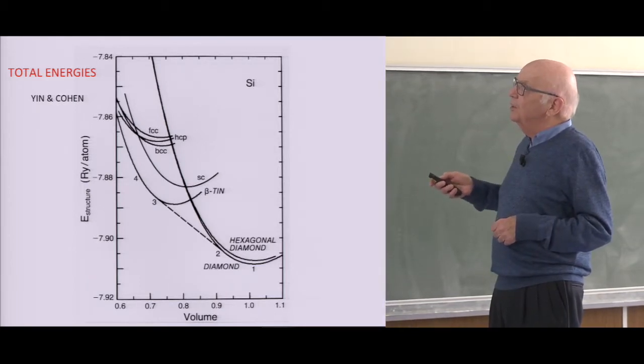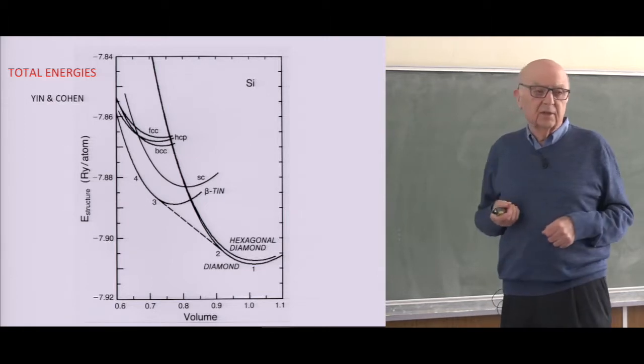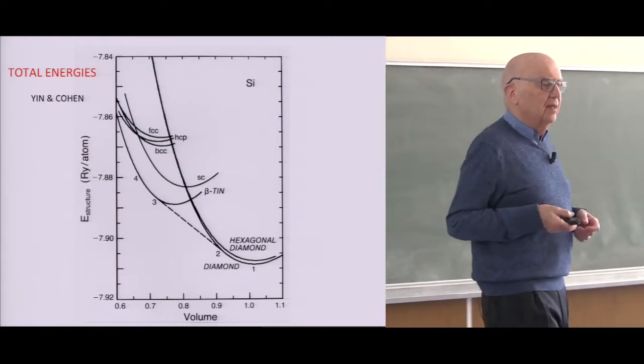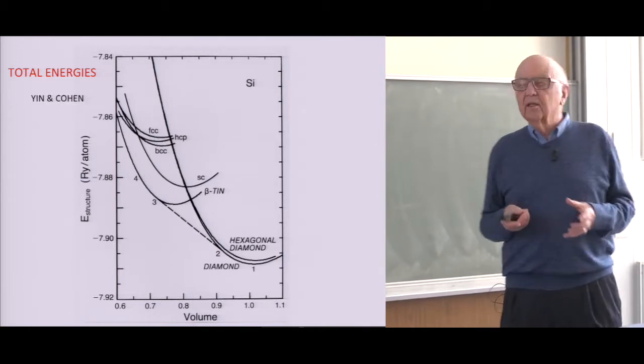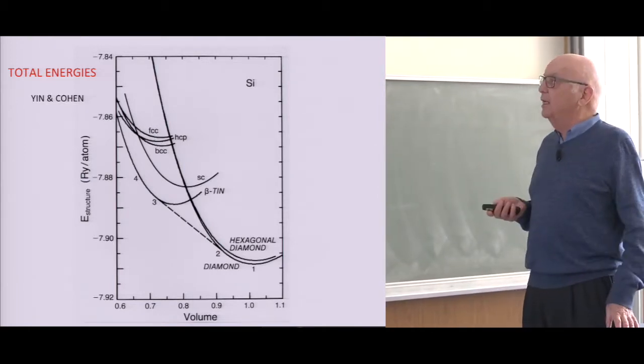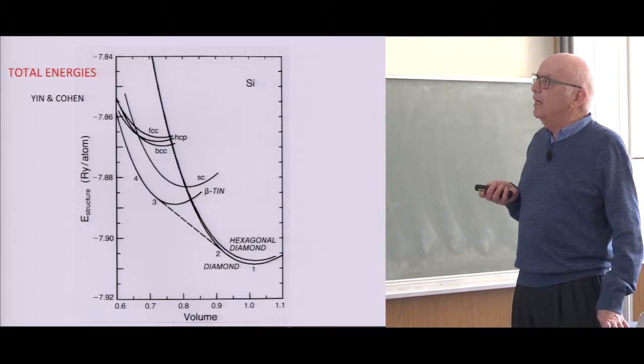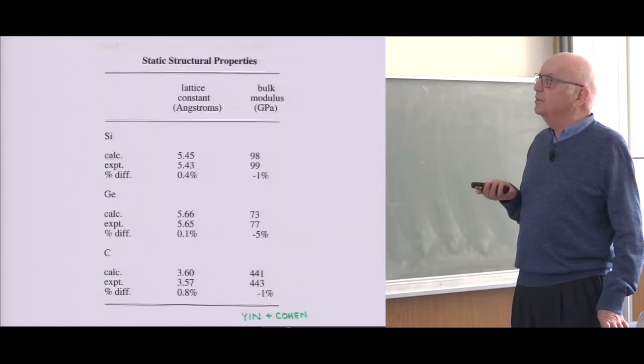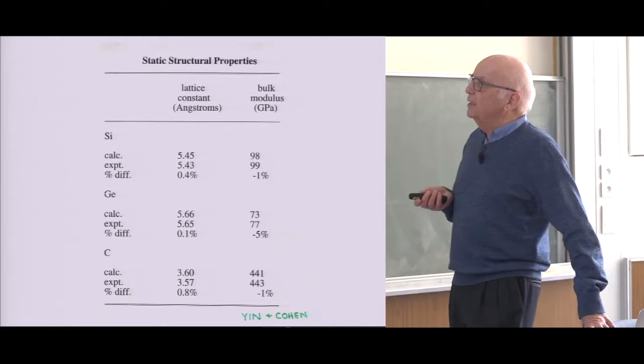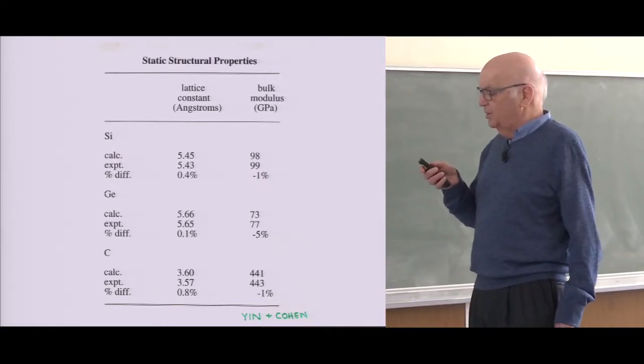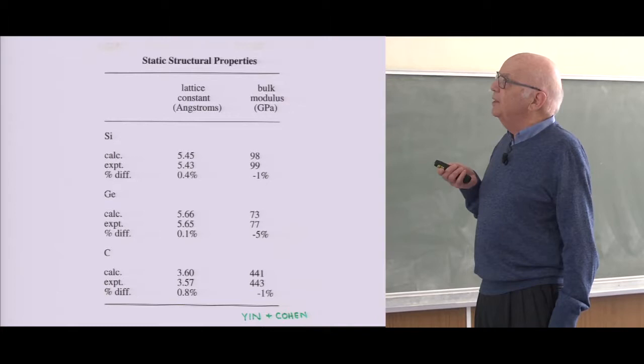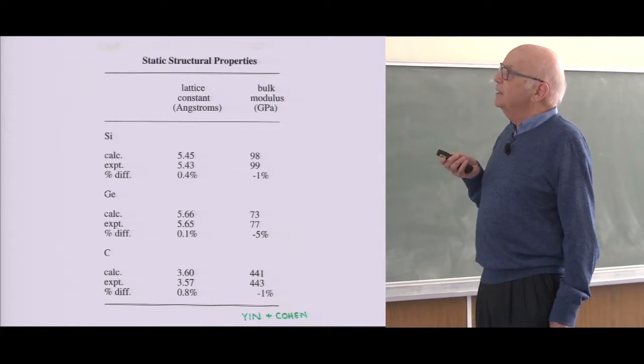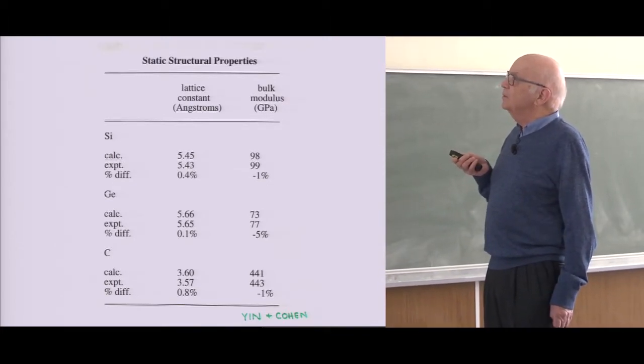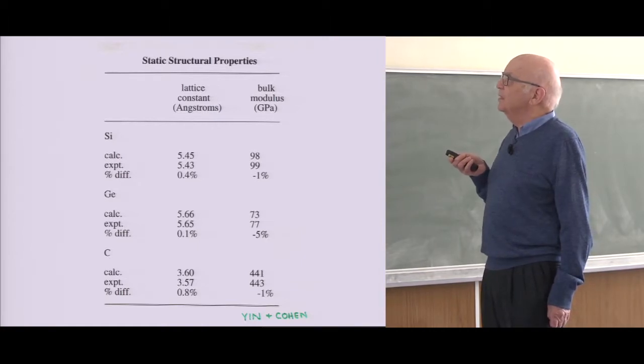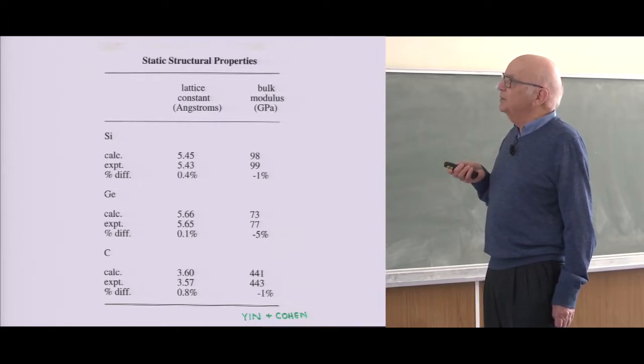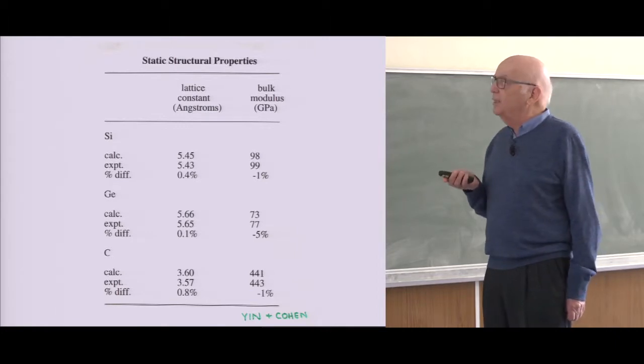Using this theory, you could predict all kinds of other structures of silicon, and then they were found afterward. So you can calculate the total energy and evaluate what happens as a function of pressure. And it's very precise. This was very early. This is the first one, just to give you some idea. If you compare the calculated lattice constant with experiment, it's within 0.4%, and the bulk modulus within 1%. Here's germanium and carbon.